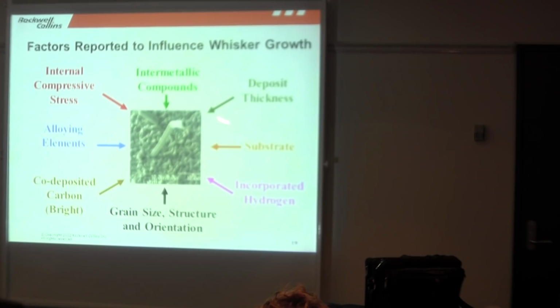The deposit thickness. Thin coatings tend to whisker more than thick coatings. And part of that is how stressed the coating is. And that's something I'm going to talk about we can use a little bit. What's my substrate? If I'm on alloy 42 or ceramic, that's a whole lot worse than being on copper. You know, it just depends on what that substrate is giving an influence. It's putting stress, it's adding to the stress of the finish, and that will help influence what's going on.